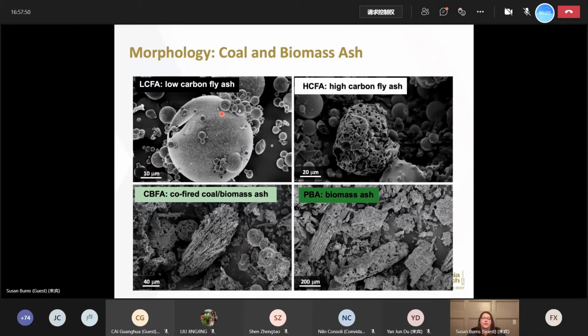So here in the upper left-hand corner, what we see is a very high quality fly ash, very clean cenospheres, perfect ash for use in high quality concrete. When we look here on the right-hand side, what you'll see again is that residual organic structure. So these are total organic carbons of some form that for whatever reason have not been combusted. These cause us problems and generally are a little bit more tricky to deal with.